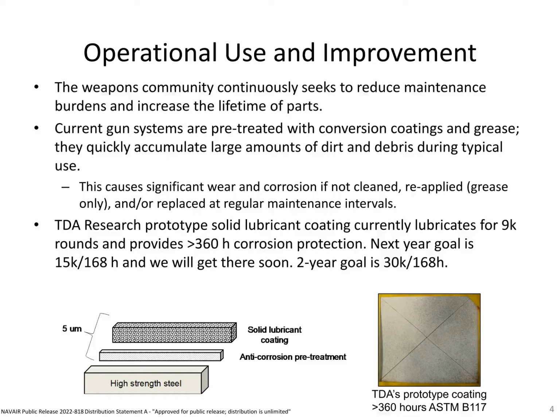And the solid lubricant top coat is just a dip coat that is cured at about 200 degrees Fahrenheit for an hour, and that's just to drive off some of the processing solvent. There's no actual chemical processes happening that are required to be heated.